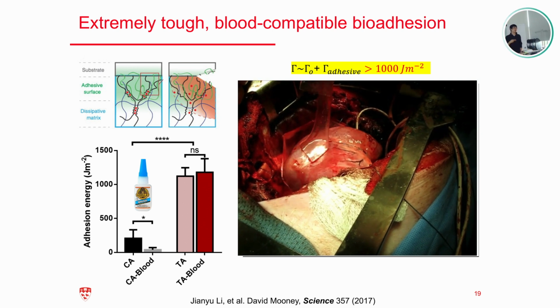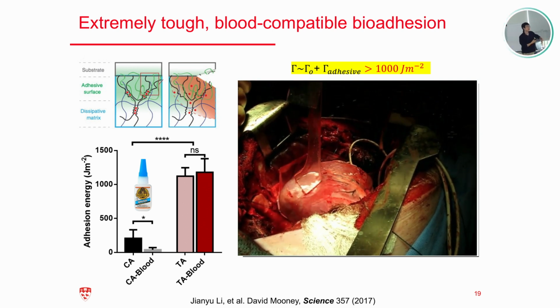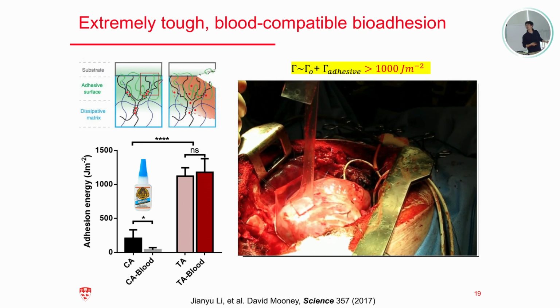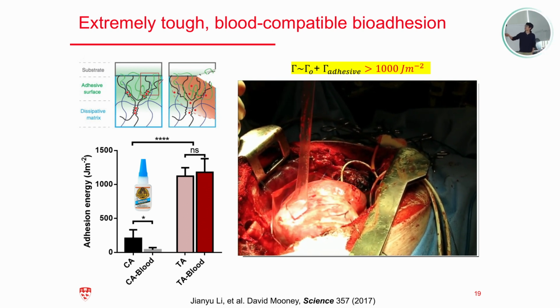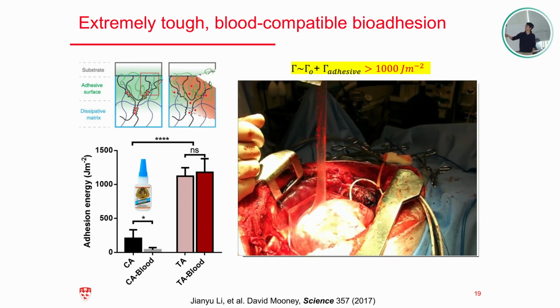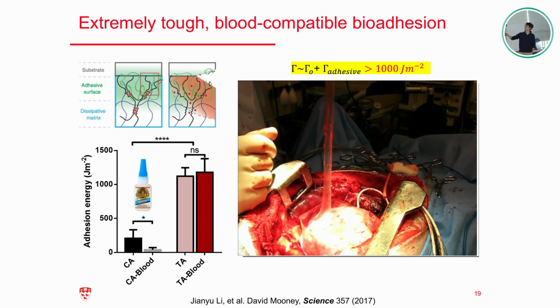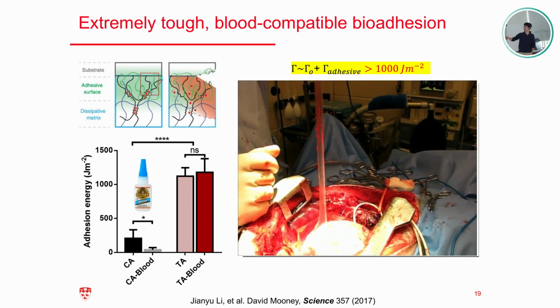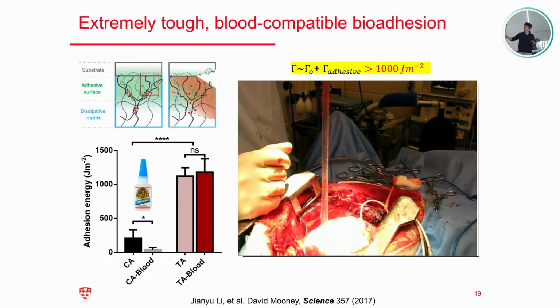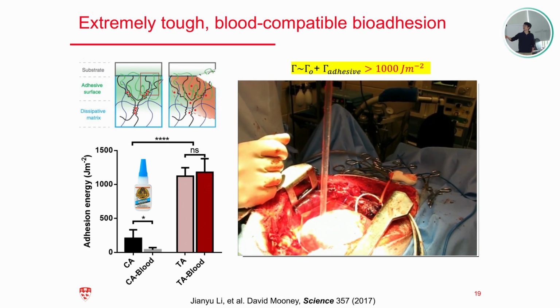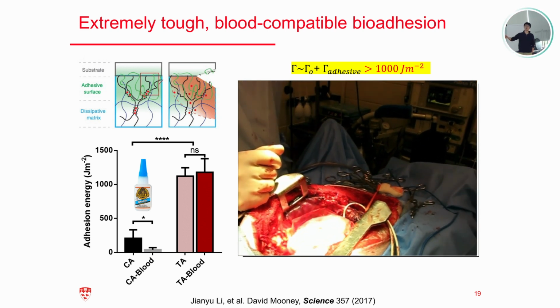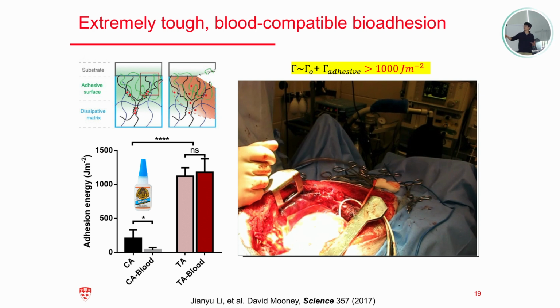All the chemistry we use, the hydrogel matrix and the carbodiimide chemistry, are water compatible. So our system is insensitive to blood exposure. You see, blood exposed or not, it doesn't matter. In contrast, you may know that superglue, which is often recognized as the strongest adhesive, doesn't work when you apply it on a wet surface, because a little bit of water moisture will trigger rapid gelation of the cyanoacrylate and limit its engagement with the tissue substrate. So that's why it's not blood compatible.